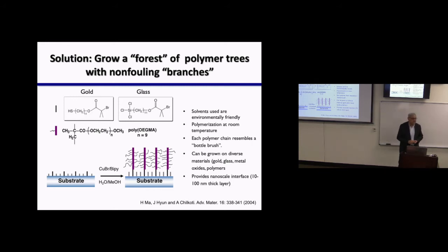Because when you attach polyethylene glycol, which is a linear polymer, to a surface, you will reduce protein adsorption, but you can never get rid of it because, the way people were doing it, they were synthesizing PEG in a test tube, in a beaker, and then attaching it to a surface. What they really needed and wanted was a forest of PEG on the surface, but the analogy I use is it's like trying to plant a forest by growing up saplings in a nursery, uprooting them, putting them on a helicopter and throwing them at the surface.